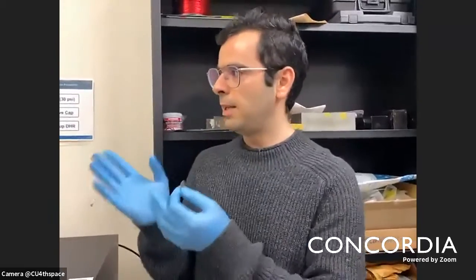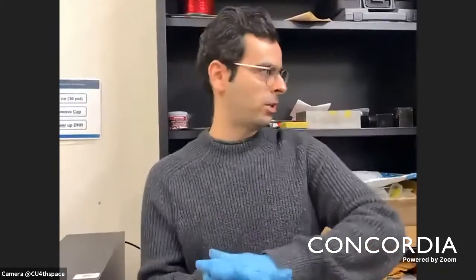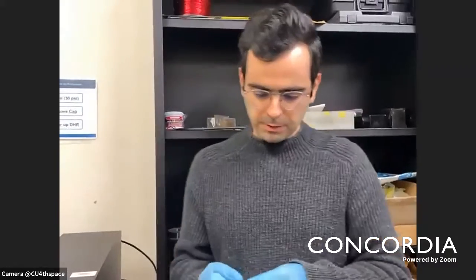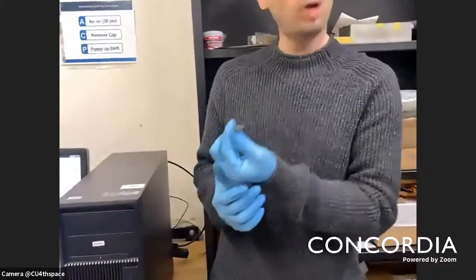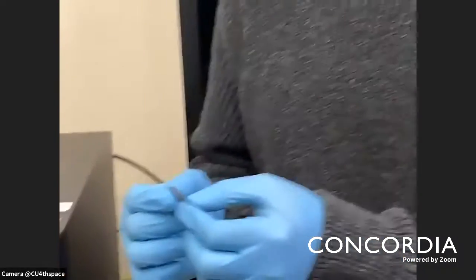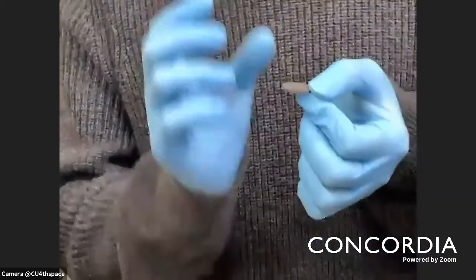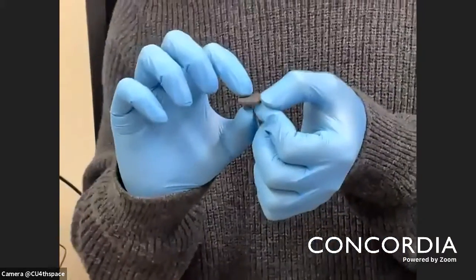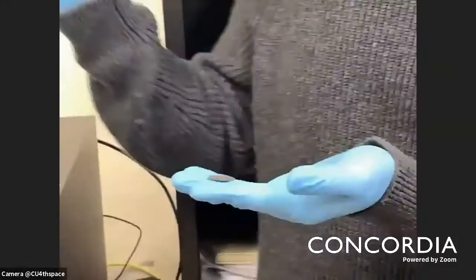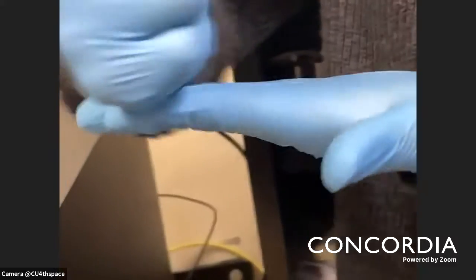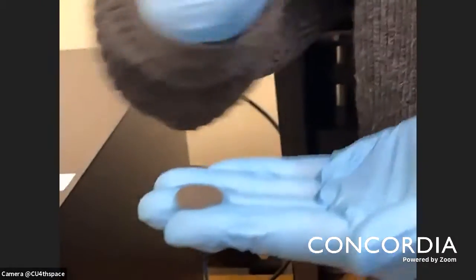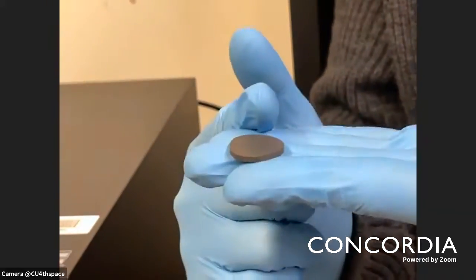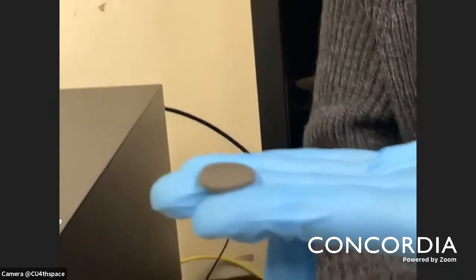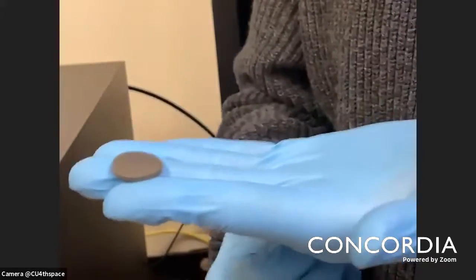So this device is mainly dedicated to shear mode characterization. A specific sample geometry should be applied under this rheometer, mainly a cylindrical sample, diameter of 20 millimeters and thickness of 1 to 2 millimeters. And this spindle from the top goes down and attaches to this MRE sample and creates rotational deformation simultaneously, perpendicular to the surface of the sample. There is a magnetic field coming from this electromagnet inside.